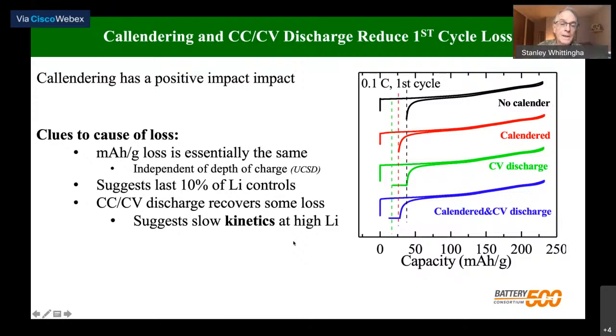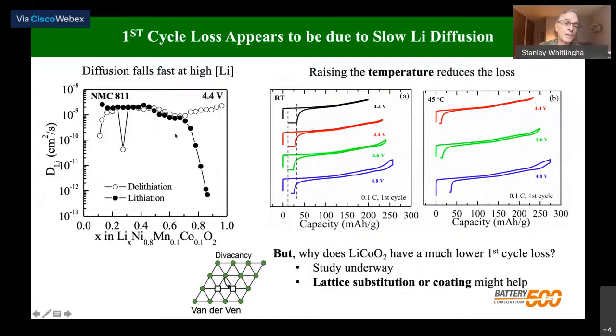So we went in and measured the diffusion coefficient. The black circles here is lithium in diffusion. So we're putting lithium in. And you can see once we get to about 80% lithium, the diffusion coefficient falls off by about 3 orders of magnitude. So this is what's causing the problems. Taking the lithium out, which is the open circles, it's not so much a problem except at the very end, a little bit here. So this material is amenable to fast charging.